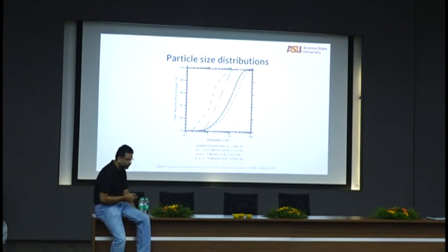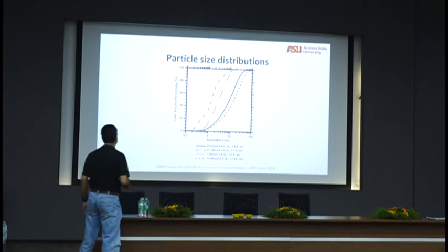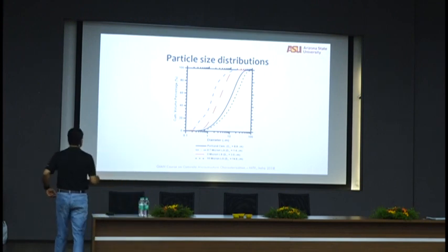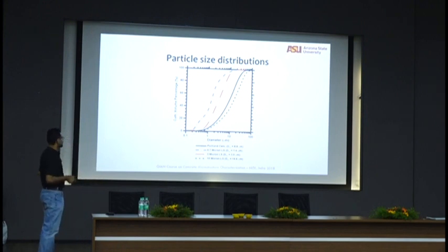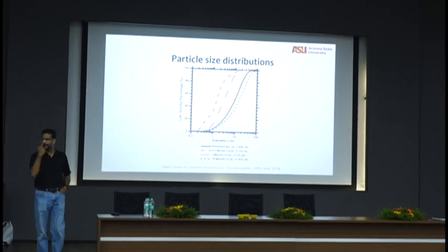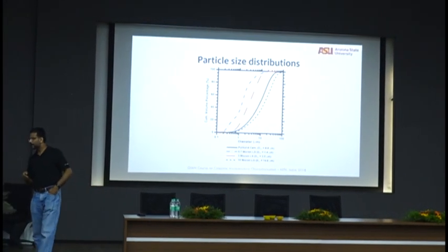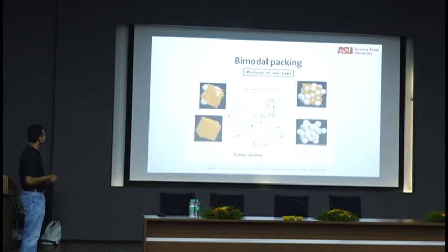size distributions, when we talk about plain cement, so we'll start with that. This is a fine Portland cement, probably a type 3 cement, which is high fineness. So D50 is about 9 microns. If I have 3 different sizes of limestones, I have a larger limestone and 2 smaller limestones. Yes, the same idea that I talked to you about yesterday, tweaking the microstructure.